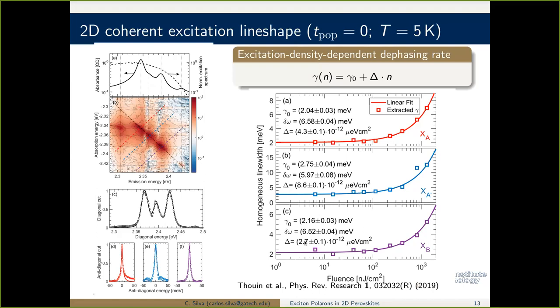And it's also a factor of two orders of magnitude different than in systems like molybdenum disulfide or molybdenum diselenide, in which we have excitons that have similar binding energies, but very different screening. The exciton-exciton interactions in molybdenum disulfide, for example, are screened to a much lower degree than they are in these systems. But each of these excitons is screened differently. Okay, that's what this delta parameter is telling us.